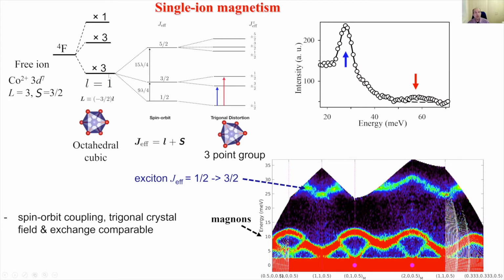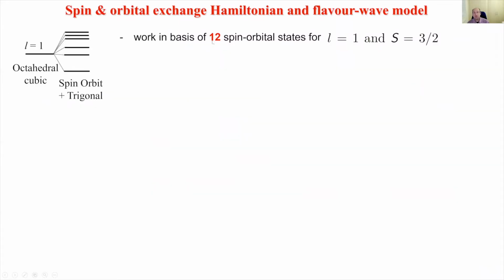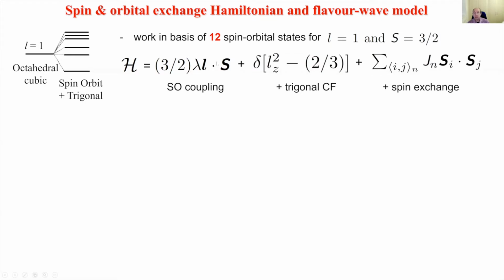if we then work in the lowest orbital triplet manifold, where we have an orbital degree of freedom L equals 1, and a spin quantum number S = 3/2, that gives rise to 12 states. So if we work in the basis of the full 12 spin-orbital states for L = 1 and S = 3/2, then we add the spin-orbit coupling, lambda L·S. We can add the trigonal splitting, which depends on the L_z component. And then we can add some exchange interaction.